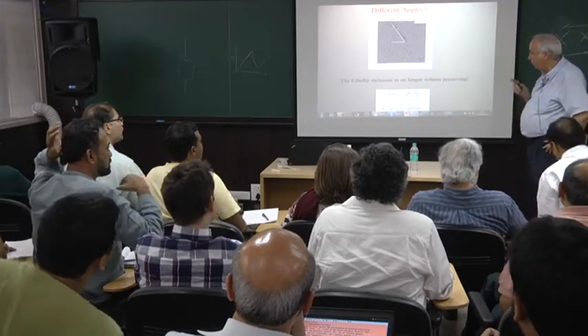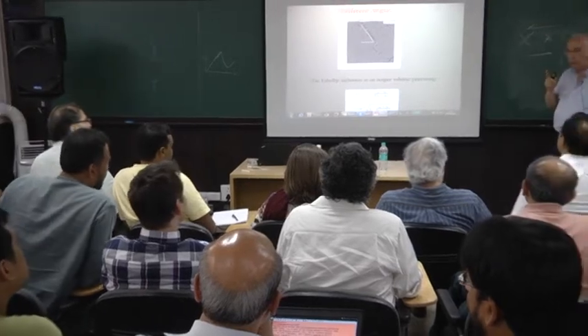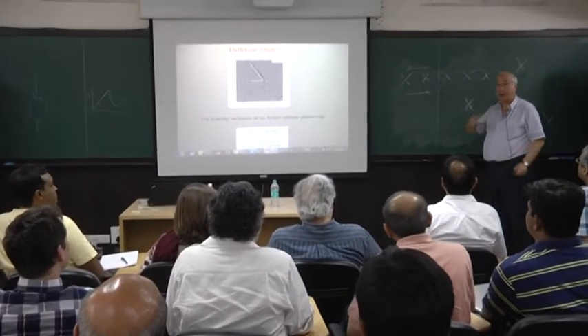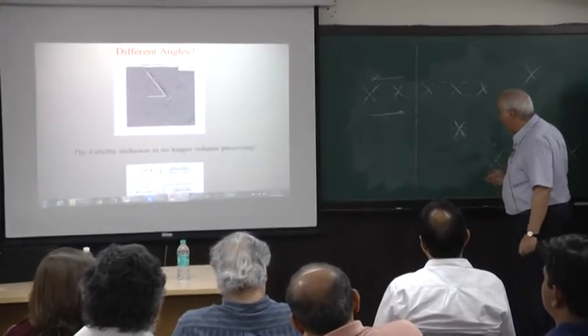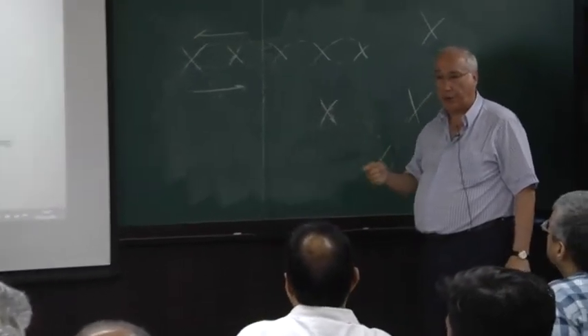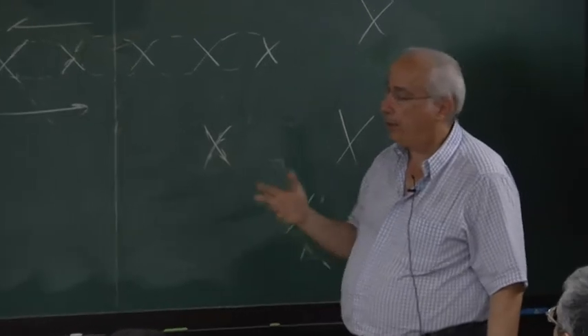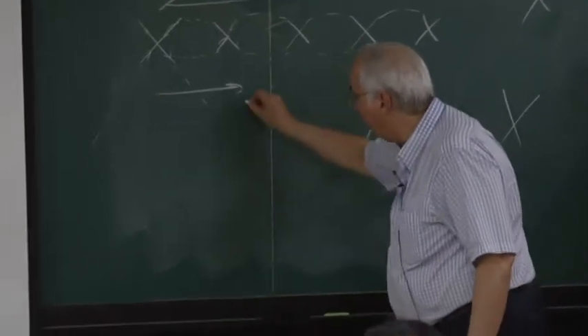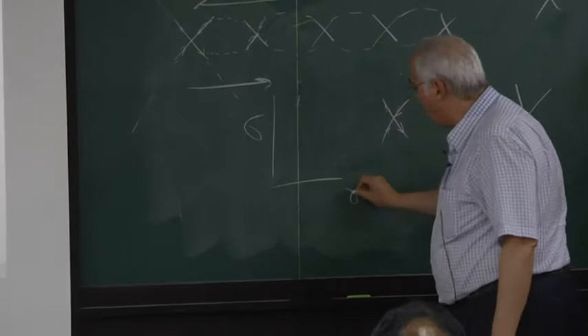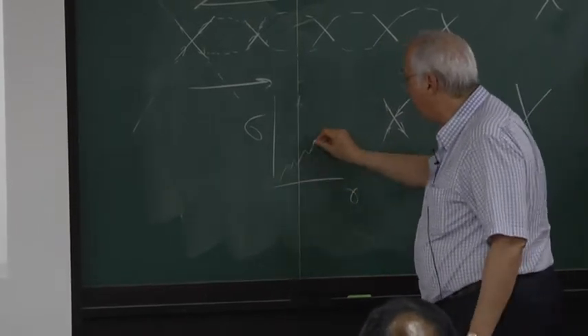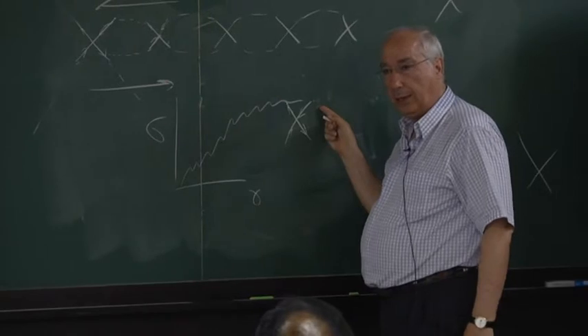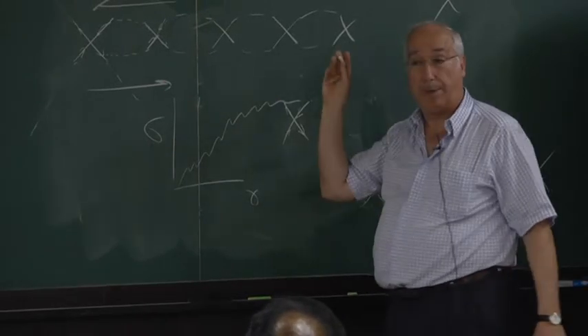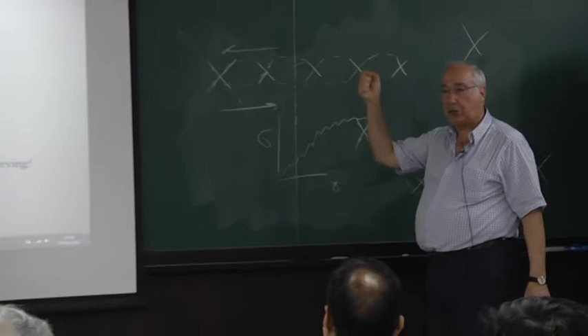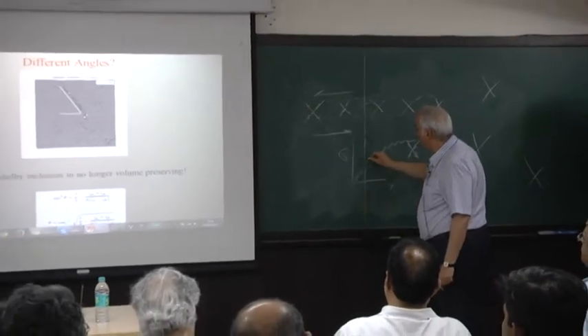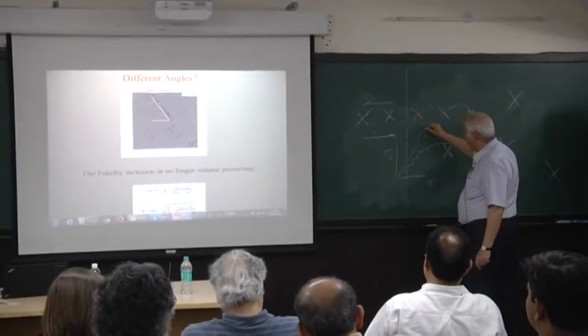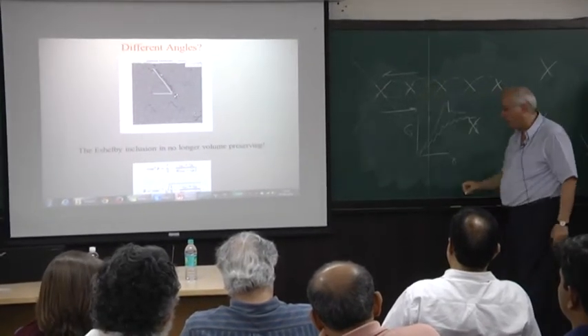Okay, so good question. I think what you are referring to, that you didn't put in a question, is that sometimes there is shear banding, sometimes there is no shear banding. The answer is in the quench rate. When you quench fast, the system is rather disordered, and then the stress versus strain curve in AQS is going to go sort of continuously into the steady state. Of course, steady state is always independent of anything. Whereas if you quench slow, it is going to go more like this, with a stress peak, and here we are going to have this instability that we are talking about.